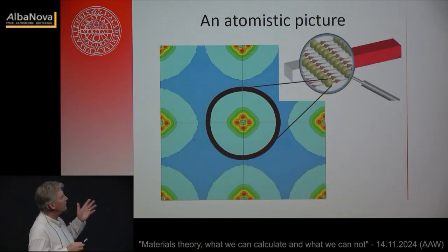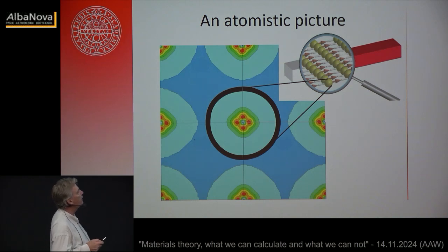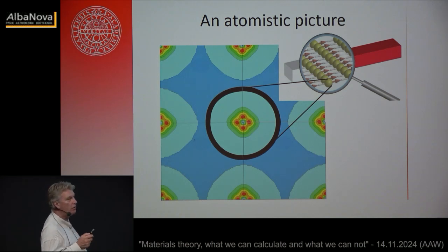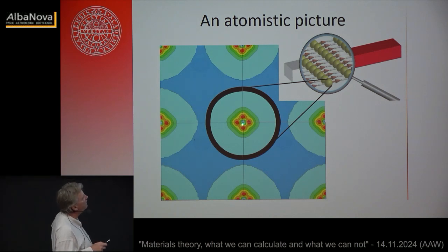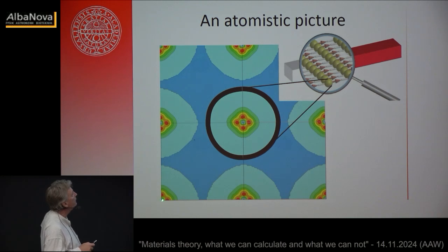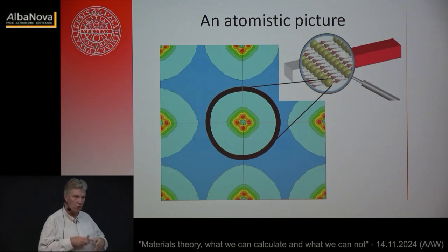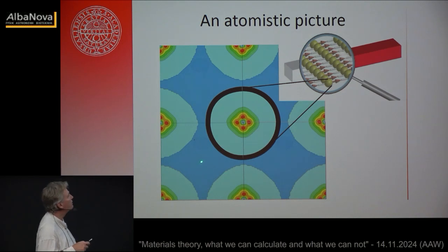There's another thing you can conclude from these kinds of calculations, and that is what's shown on this graph here. If I now look at the density of spin-up electrons minus the density of spin-down electrons, and I look at again BCC iron, but it doesn't matter what it is, any material would look the same. You will see that there are always red blobs and orange things that are close to the nuclei. Nuclei are here and here and here and here, and there are bluer regions in between. The redness indicates high spin density, so a large part of the magnetism comes from there. And the blueness means basically absent spin density, nothing much happens there.